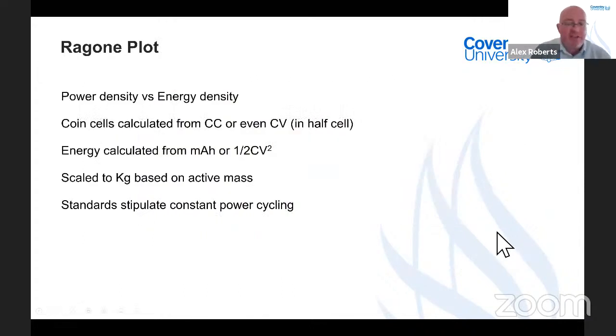Let me give you an example in supercapacitors. The Ragone plot is used as a fingerprint metric and a performance indicator for supercapacitors. It's simply a plot of power density versus energy density. And it's very, very common in the scientific literature, when people are looking at a new material, to calculate power and energy densities from constant current cycling in a full cell, or even from cyclic voltammetry in a half cell. And then they'll calculate their energy density and their power density and scale these numbers up to a value in kilos and say, this is my power and energy density. And it is so many times higher than the leading manufacturer.